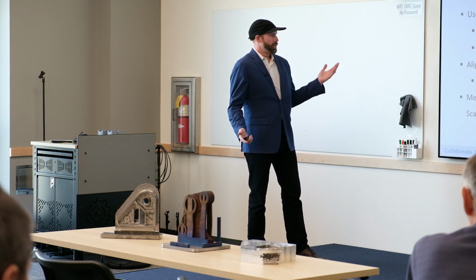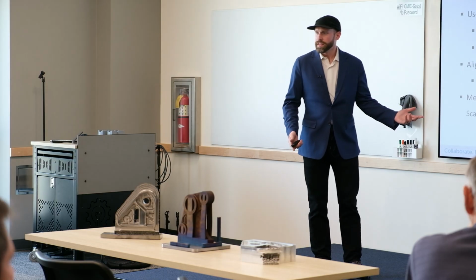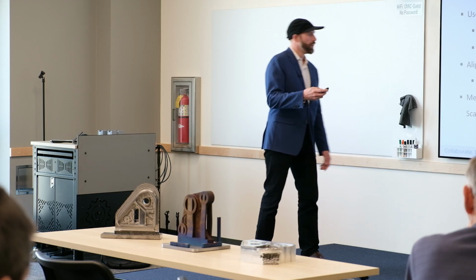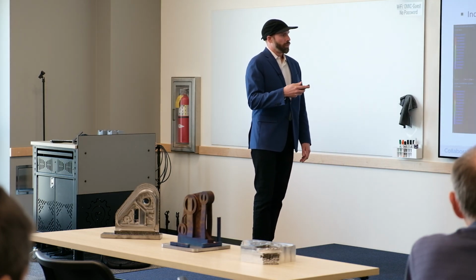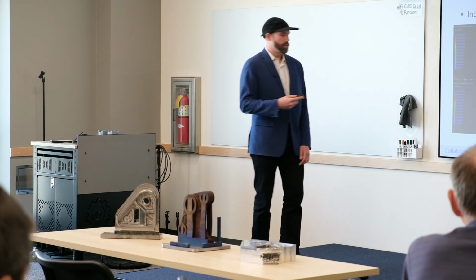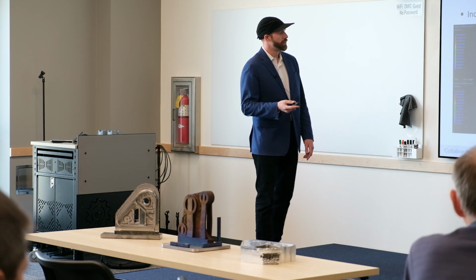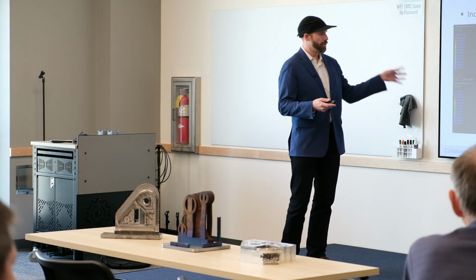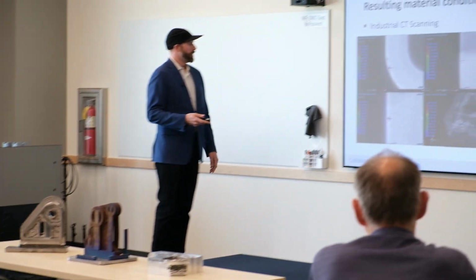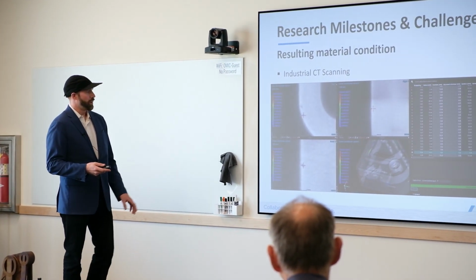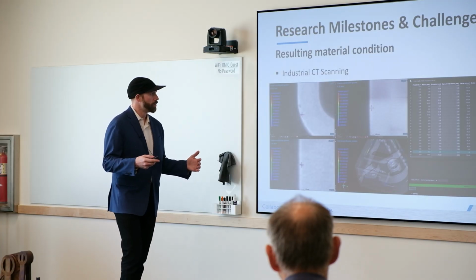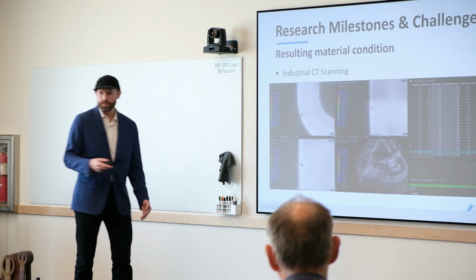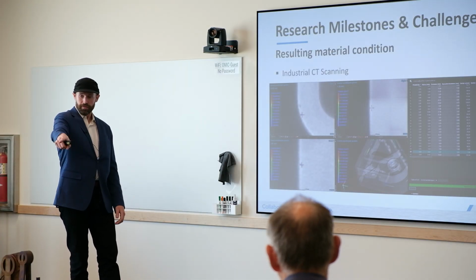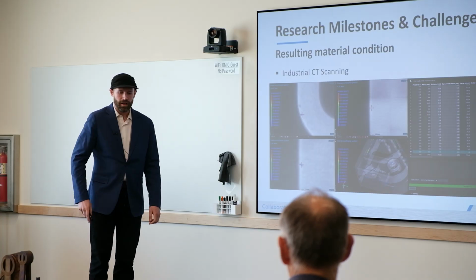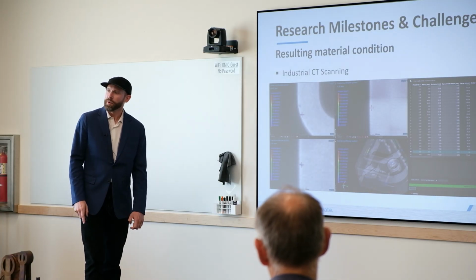And we want to measure all of these parts using industrial CT scanning. So we want to look inside of these pieces and see what kind of voids we squeezed out of them, right? We were working with the scanning company that we partnered with for this project, and they were able to give us some very good feedback. So this is the titanium 6Al-4V part, hipped and final machined. They're able to get down to about 140 micron voxel size for a part of this density and size. Pretty difficult for industrial CTs to make that happen.